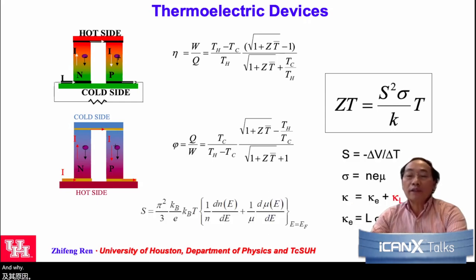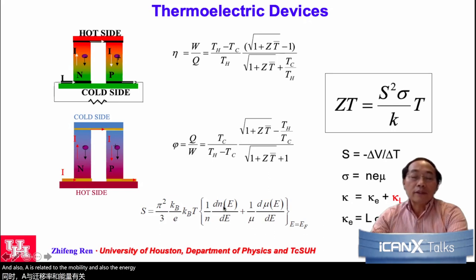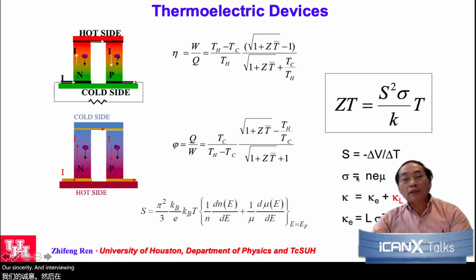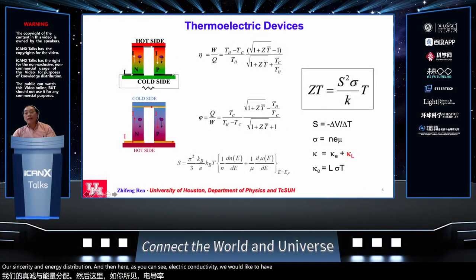And why is it so? That's because these three physical parameters are interrelated. As we know, the Seebeck coefficient is inversely related to the carrier concentration, and is also related to the mobility and the energy density and energy distribution. And then here, as you can see, electric conductivity, we would like to have high electric conductivity, but high electric conductivity requires a very high carrier concentration, which will reduce the Seebeck coefficient.